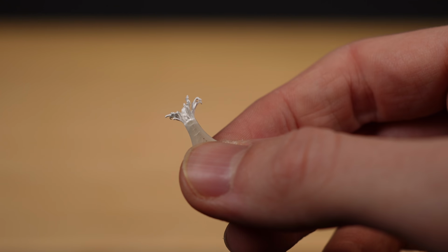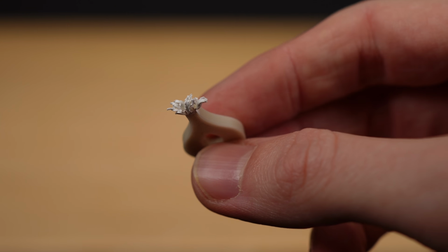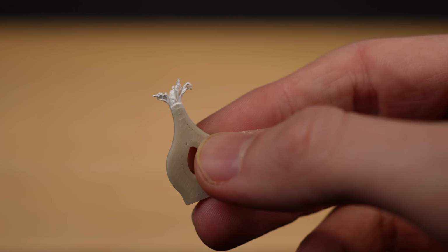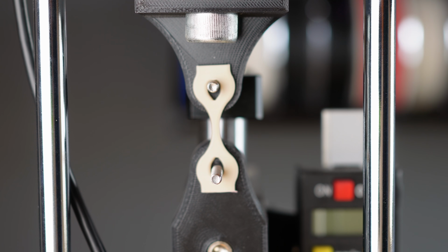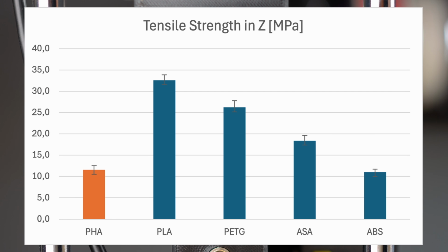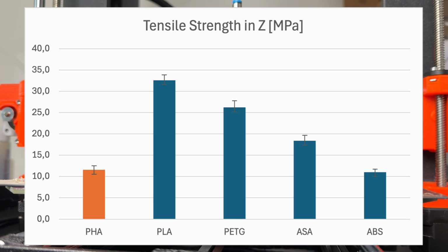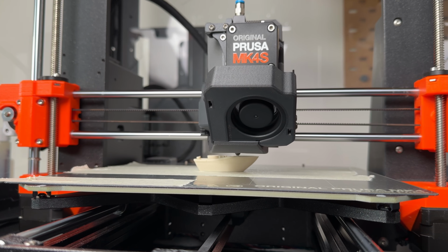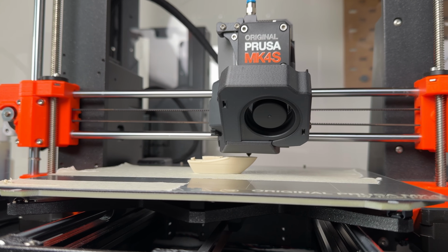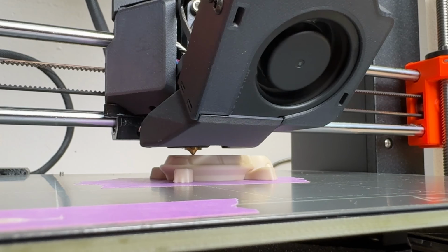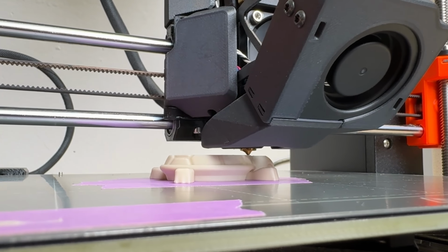What I found to be interesting is the way the samples broke apart. It is usually a sign for rather bad layer bonding, which got approved by the test in that direction. As expected, it's rather low, which is a pity. One could improve it by playing around with printing temperature and part cooling settings, but I usually don't do this in these tests as I want to compare recommended print profiles. Let me know your thoughts or experiences in the comments.